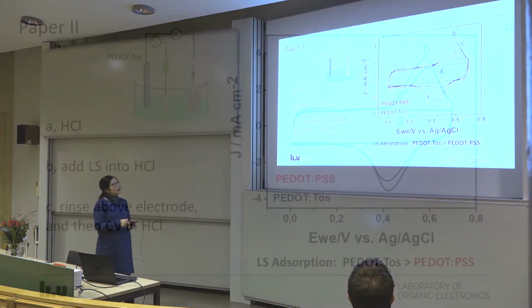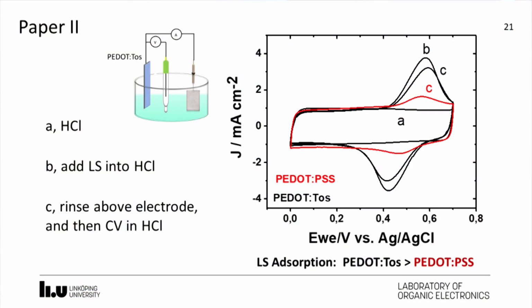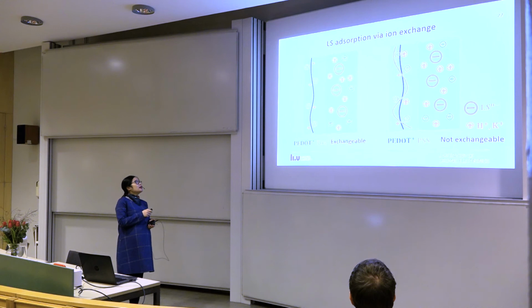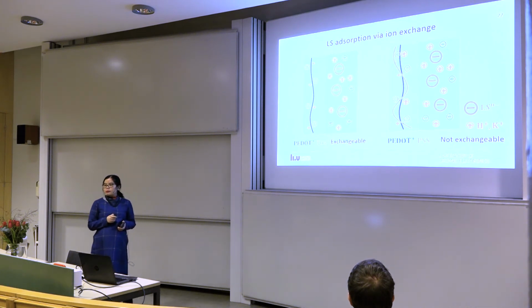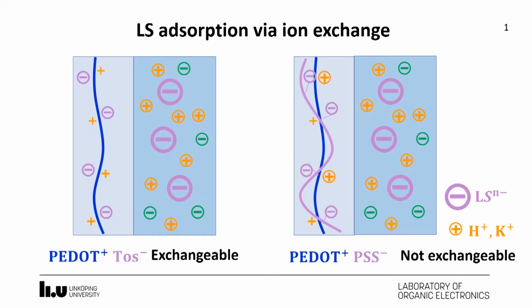And we also found that on the PEDOT:PSS electrode, less lignin sulfonate is adsorbed, as shown by the smaller peak current here. The difference between PEDOT:PSS and PEDOT:TOS was considered to be a result of ion exchange, and we also demonstrate this in the paper by QCM. As mentioned, lignin sulfonate is a polyanion. It carries a negative charge when dissolved in electrolyte. So